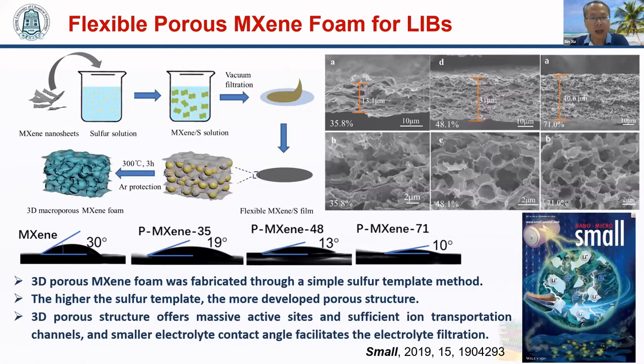Transforming 2D MXene nanosheets to a 3D porous architecture is also an effective way to solve the restacking of MXene films. As we know, the template method is a very effective method to create porous structures. Sulfur is easy to control in particle size and can be easily removed by sublimation at a temperature higher than 300. So we use sulfur as a template to create a porous structure by mixing the sulfur and the MXene in solution, followed by filtration and thermal treatment at 300 for 3 hours to remove the sulfur. We can see that a well-developed porous structure is created. The higher the sulfur template content, the more developed porous structure can be obtained.